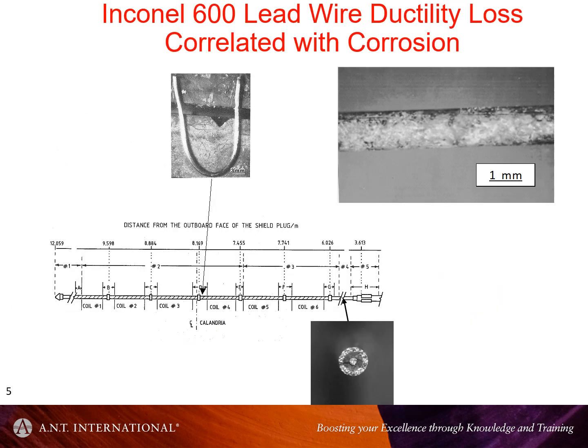So what I saw when I just started work at CNL was that, being responsible now for the surveillance program of these flux detectors, it was very clear that there was something to do with the temperature. So basically they were encapsulated in a zirconium alloy tube, but obviously the helium gas was released at some point. It's funny, being helium, but also they just leaked out, replaced by air. Air is not as good a conductor, and these things got hot.